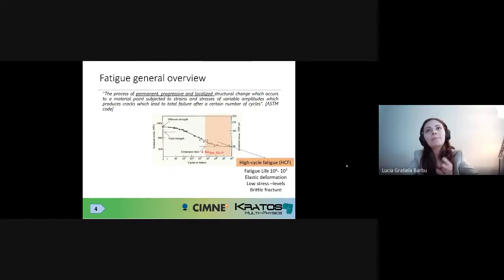For instance, in this right part of the curve, we can see the behavior of high cycle fatigue. High cycle fatigue is characterized by quite large fatigue lives, in the order of millions of cycles, hundreds of thousands of cycles. Primarily, we have elastic deformation inside the material, and the stress levels are quite low, below the yield threshold. The fracture associated with high cycle fatigue is brittle, and I want to say that this is what was initially understood as fatigue.